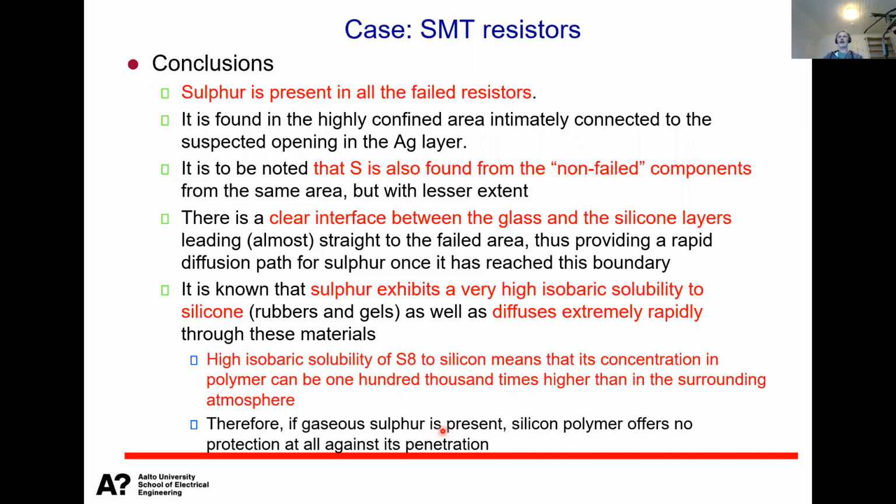So if you have parts-per-million concentration of hydrogen sulfide, you might have even a few percent sulfur in the actual silicone. So there's a driving force for reactions.